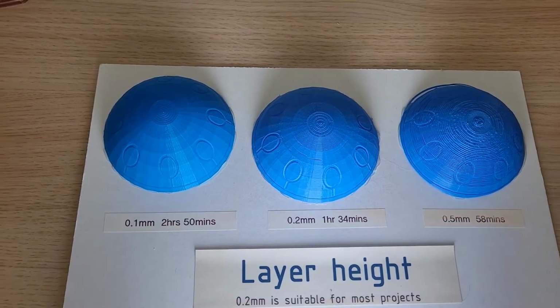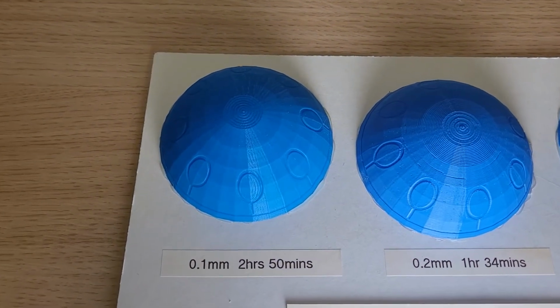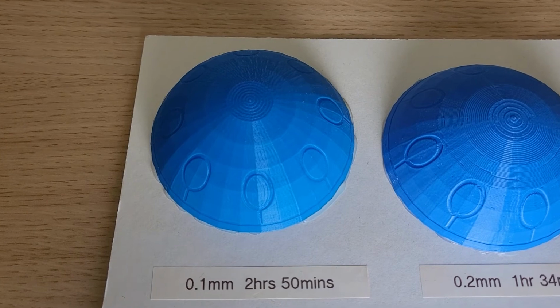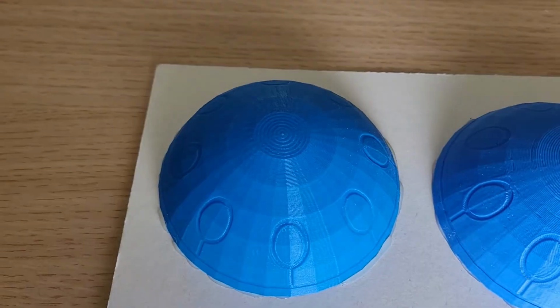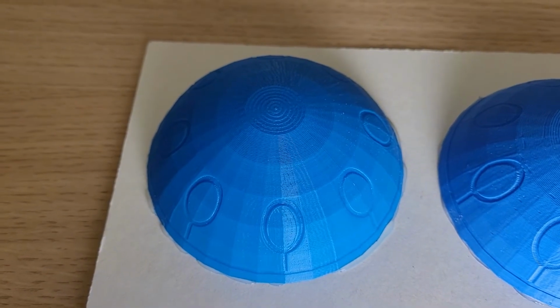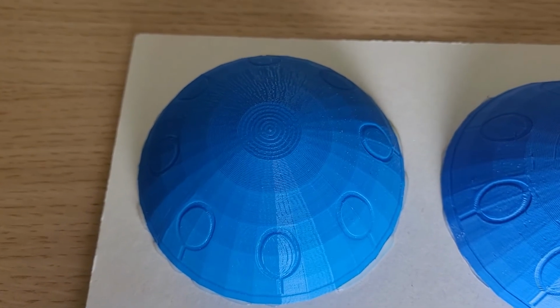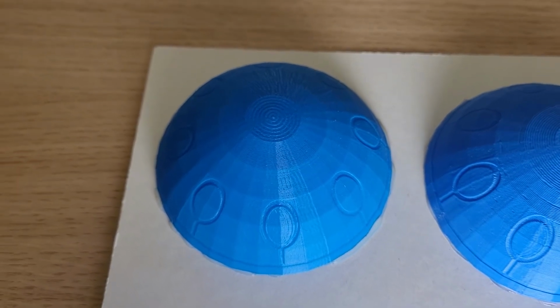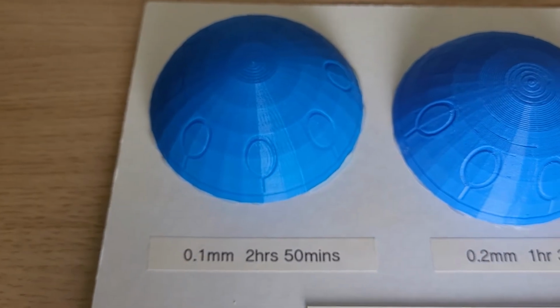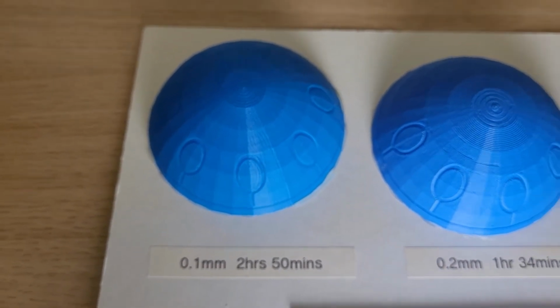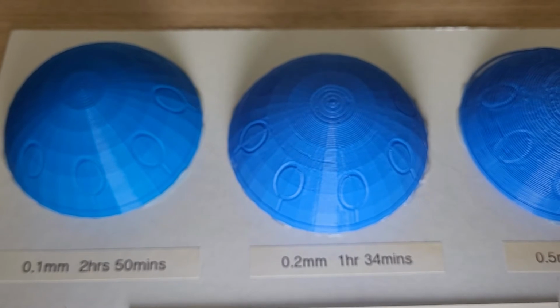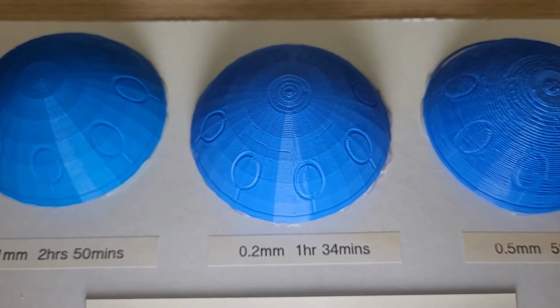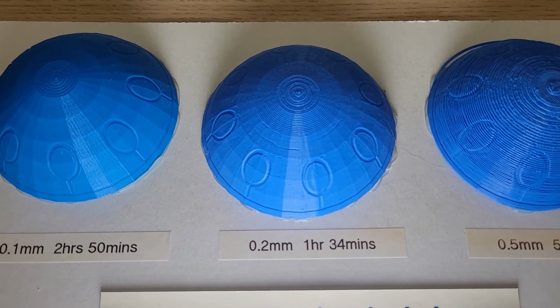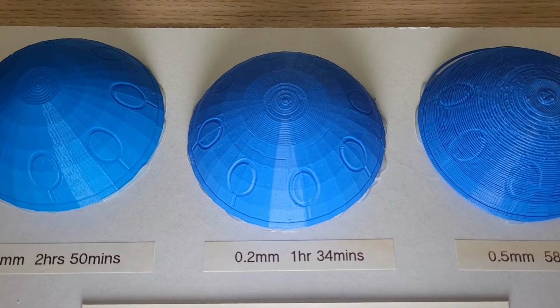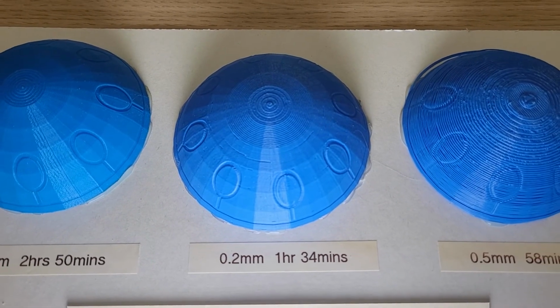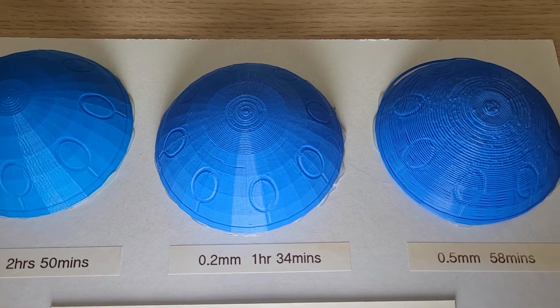So let's start with a fine setting. This is 0.1 millimeters. If I can zoom in there, you can see that's quite fine layers. But from the top, there's a few steps you can see. Now that particular print has taken 2 hours 50 minutes, and we go to a 0.2 millimeter setting. You can start to see some of those lines are a bit more prominent there, and that's 1 hour 34.